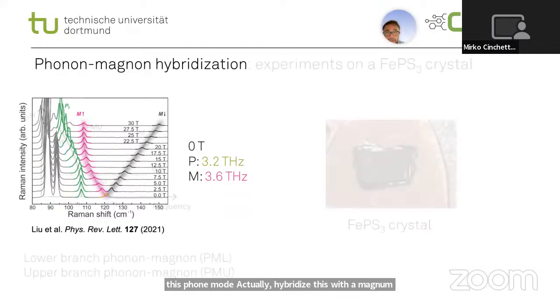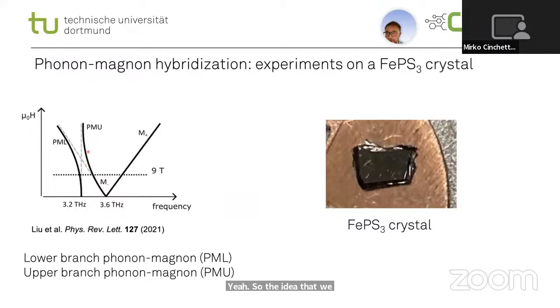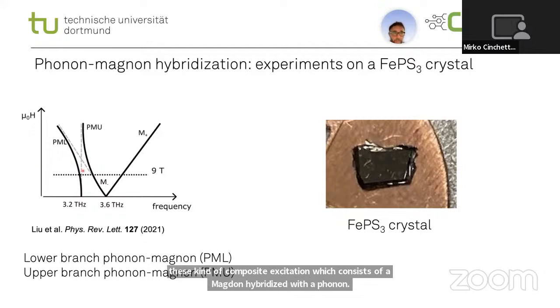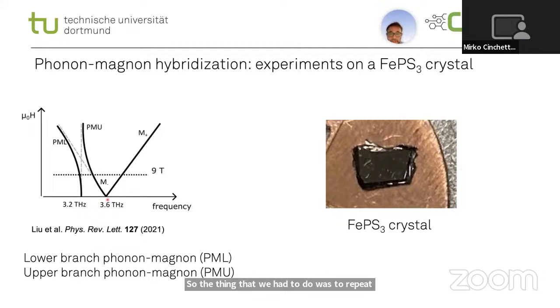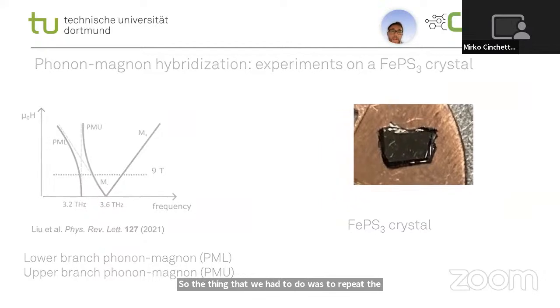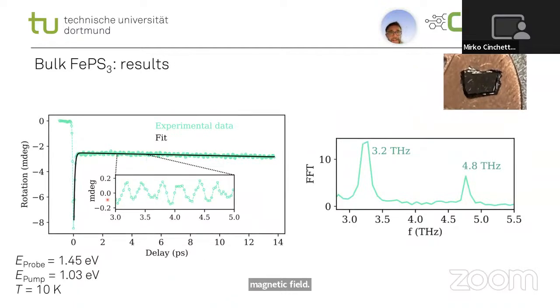The idea that we had now was to exploit this hybridization to see if we can also optically generate this kind of composite excitation, which consists of a magnon hybridized with a phonon. So we had to repeat the experiments as a function of an applied magnetic field. These experiments were done on crystals for stability issues instead of on the flakes. We see the same oscillations as in the flakes here at 3.2 terahertz. This is the mode that we are interested in.